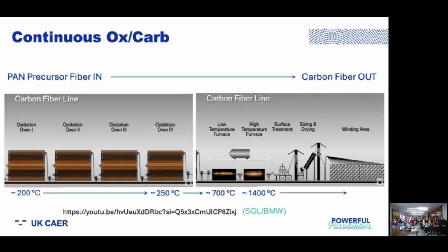But I want to point out that the oxidation process is by far the bottleneck of producing carbon fiber. These are huge oxidation ovens, and the fibers go through this in a serpentine fashion, through each of these, with residence times on the order of about 100 minutes.